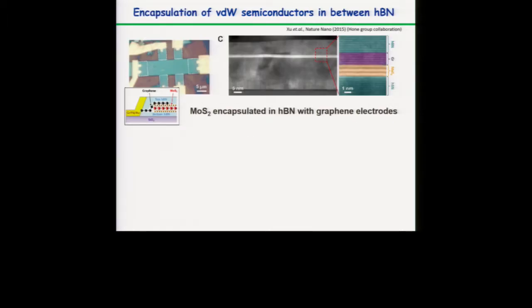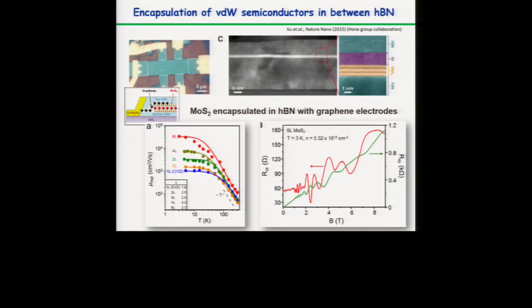Okay, but the talk is about optoelectronic devices, right? So we need to make contacts first onto these semiconductor materials. Initially, they were making contacts on TMDCs, on MoS2, using graphene. It was proved in this paper that graphene can make a good contact on TMDCs, but this is only on about 6 layers of MoS2. They also showed that in 1 layer in CVD and highly doped MoS2, they can also make good contacts. But it's not easy to make contacts on single layers.